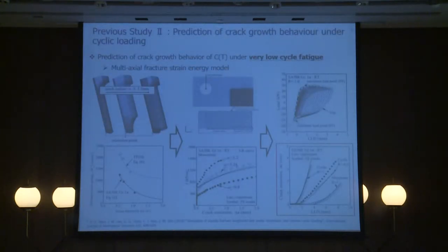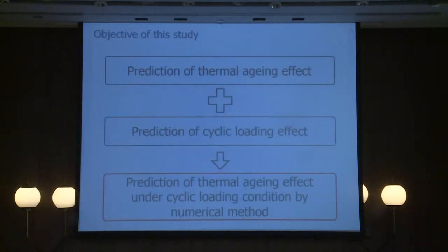Also, this is our previous study. In this study, we predicted the crack growth behavior of SA508 material on a CT specimen under very low cyclic loading condition. We applied the strain energy based damage model, and by this model we can predict the fracture toughness of the CT specimen. So in this research, by combining those 2 previous studies, I predict the thermal aging effect under cyclic loading condition by numerical method.